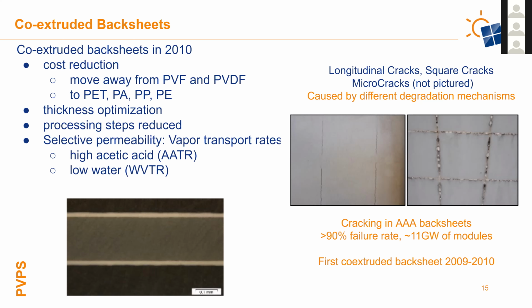But as we found with our first co-extruded backsheet polyamide, what we got was a lot of failures. Gernot went over this a bit, but I want to touch on it again: the degradation mechanisms in these failures are not exactly the same.